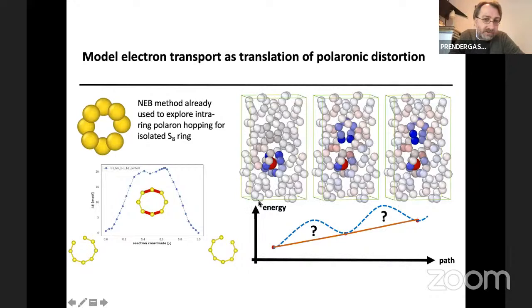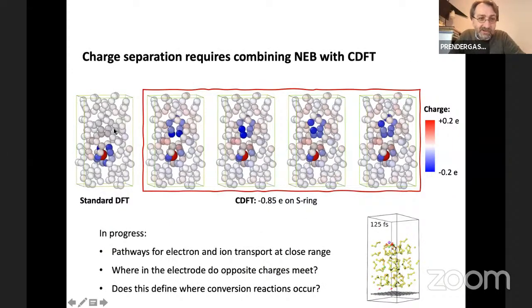The literature has already explored the isolated charges and their kinetics for moving through these solids, but not when they're close to interacting with each other. And there's definitely a strong slope already. So if we were to just do density functional theory, we'd always end up with this end state where the charge, the electron, is sitting around the lithium and we can't escape that. But what we'd like to know is, no, it has to come here from some point, and there are barriers to its movement. So what are those barriers, and what would be the rate of charge transfer and recombination? Okay.